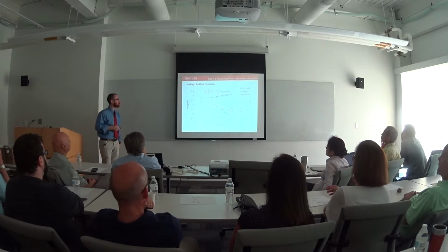So in order to prove that we have the critical conditions, I next looked at some more traditional methods for characterizing the critical conditions. What we show here is that as a function of our adsorption potential, the number of adsorbed monomers is a linear function of the adsorption potential up to a point, and that point is our critical condition, which is exactly the same as what I found for the incremental chemical potential case.